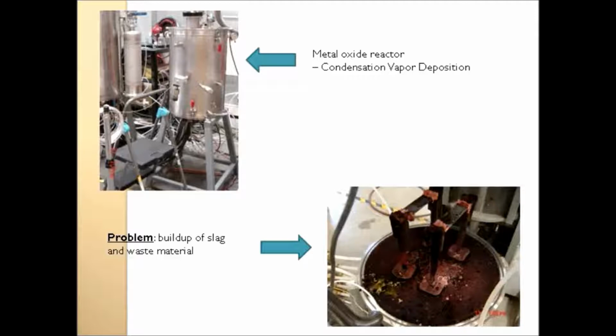The problem was that oftentimes after a run, the material is harvested and they've got to clean the reactor, and there's a buildup of slag and waste material here. They're faced with a cleaning task, and how they achieve it is by using some really standard Home Depot type tools you can go into your garage and get. A wire brush, some scrapers for removing paint, and the worker gloves up, wears personal protective equipment, and has to vigorously brush that material. You can imagine what's going to happen when you're brushing a powder like that.